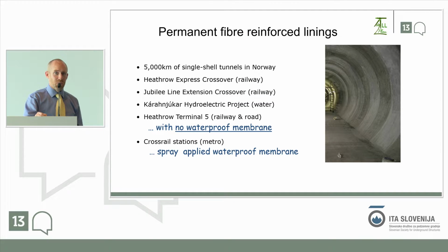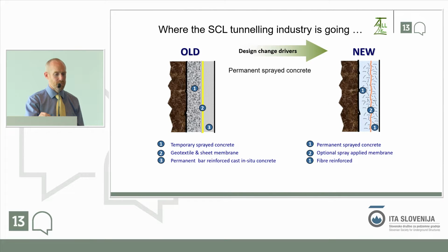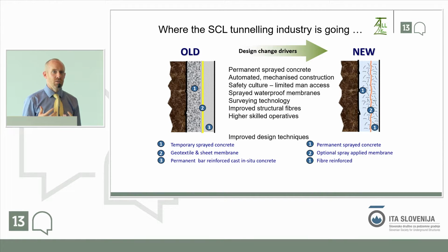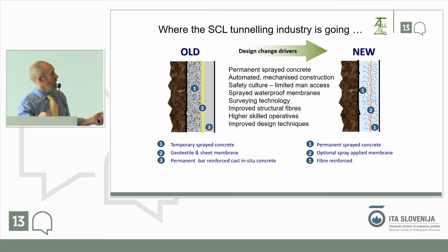Talking about tunnels, we've talked quite a lot yesterday about permanent spray concrete, and a key element in that is removing steel bars, replacing the steel bars with steel fibres. You can see some examples here showing the breadth of application. Not just hydropower projects, but also railway transportation tunnels and so on. The picture is actually from a water tunnel at Heathrow in the UK. So in terms of sprayed concretes, as I said, the trend is towards using permanent sprayed concrete. A key element in that is the use of fibres instead of steel bars, because it's inherently more durable. And I'll come back to that with a little bit more detail later.